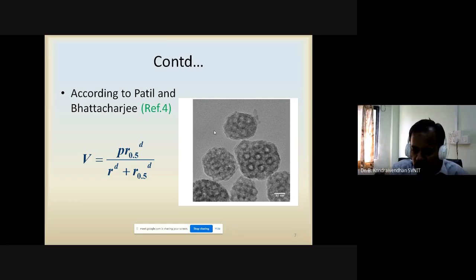Now I am going to talk about the entry radius. That is the pore radius that I am calling R.5, or I can say it's a mean distribution radius. And D is the dispersion coefficient, that is nothing but the distance between the pores. At the early stage, it should be like this: the pore sizes are very big, it may be coarser in size. Over a period of time, what will happen? A substantial degree of hydration will take place, so automatically the pore sizes will reduce. More and more C-S-H will form, so the pore size will reduce and R.5 will also reduce. But at the same time, the dispersion coefficient value will increase.